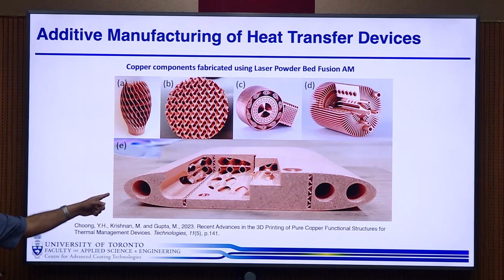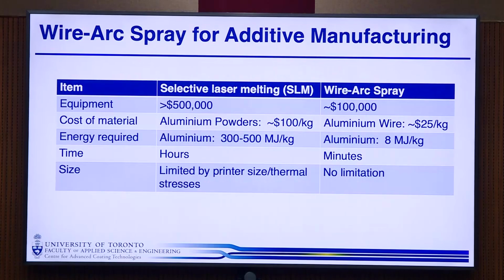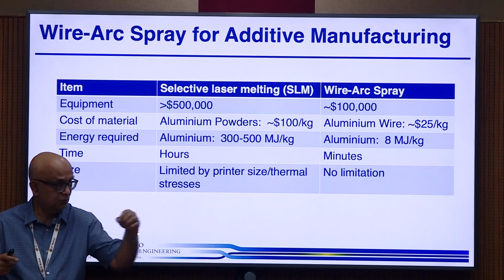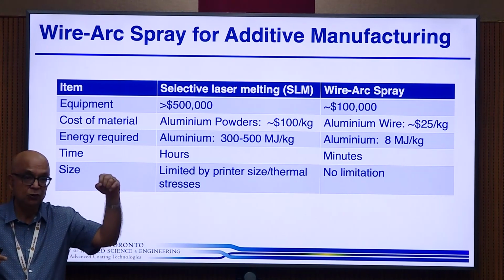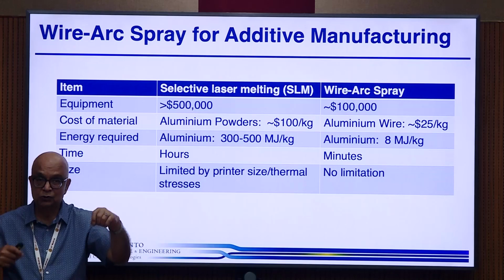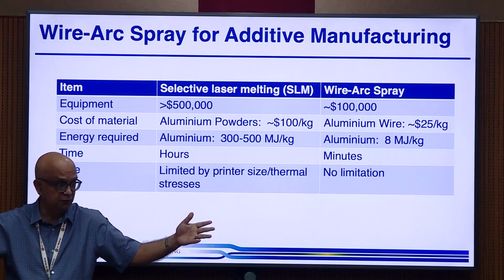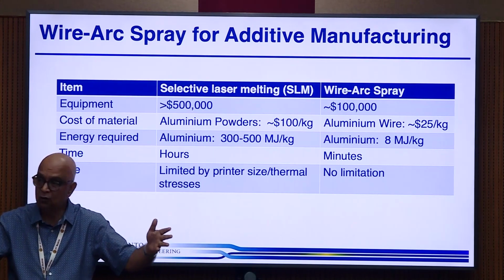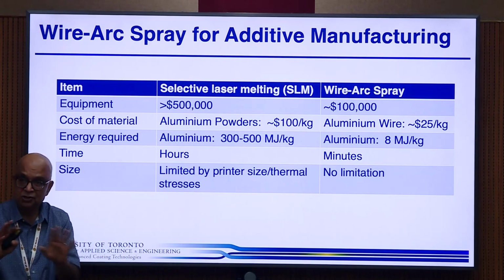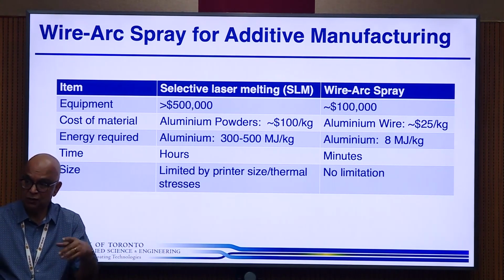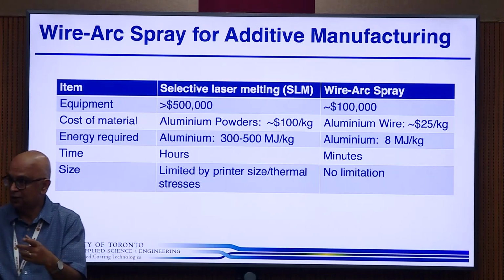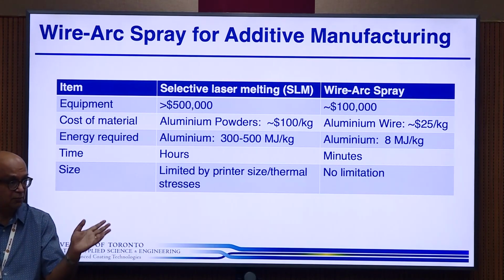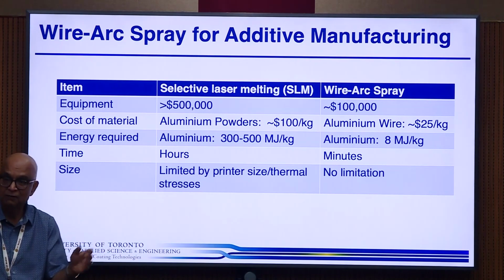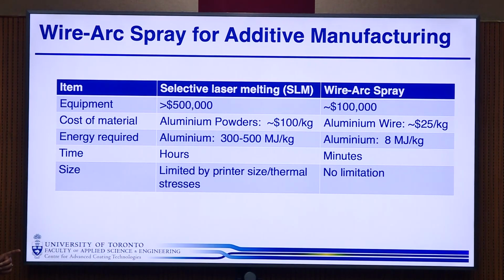The problem is even worse because you want to make this with copper or aluminum, some high thermal conductivity metal. And if this is some sort of a laser process, you need very high power lasers to sinter, because all your energy is being conducted away by copper or aluminum. So aluminum and copper are the worst metals to work with. And that's why you'll see a lot of the publications, they'll use steel, and they'll make heat sinks out of steel or something like that. And the reason for that is that they probably didn't have a machine which could do copper.